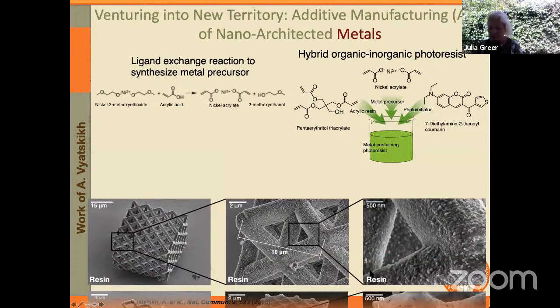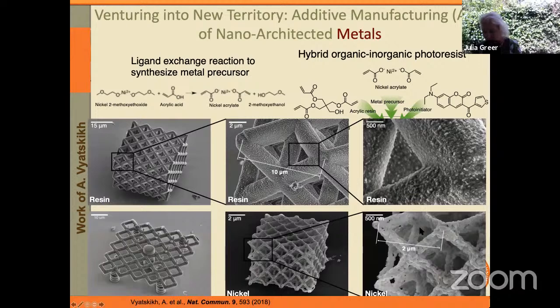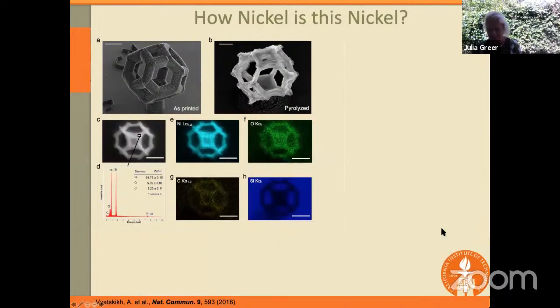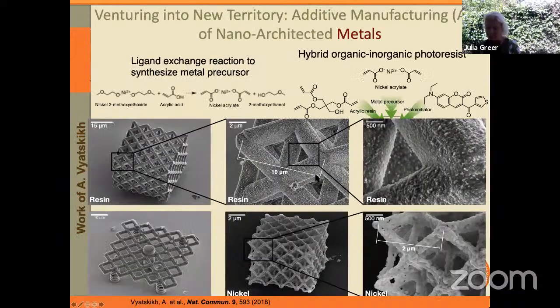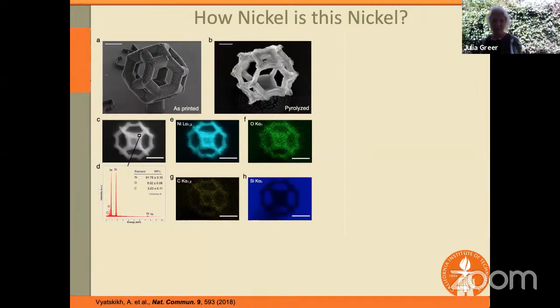Now watch specifically the size of the unit cell here. It keeps on jumping, about 2 microns. So it shrunk from about 10 microns and 2 micron diameter to about a 2 micron unit cell and 400 nanometer diameter. Now, when you look at each individual beam, you're kind of scratching your head saying, well, these are very porous. They don't look so nice. And also the question is, how nickel is this nickel? Is this really fully made out of nickel?